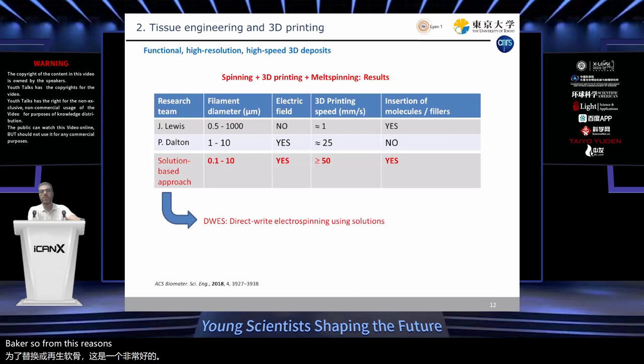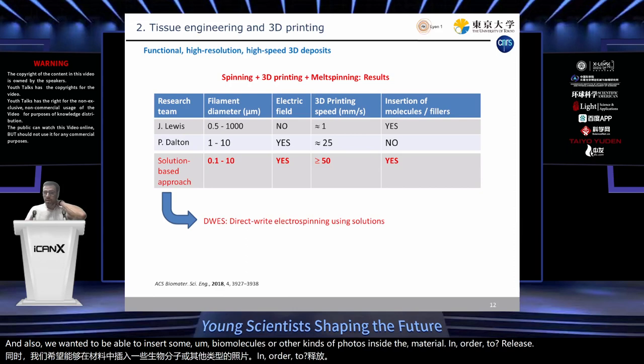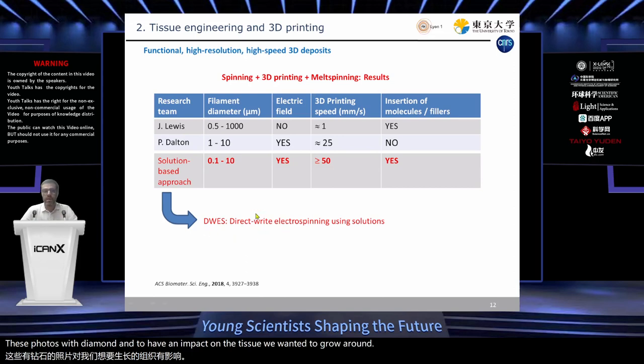So from these results, in our case, we were interested in keeping the very small size of the filaments, or the object we were printing. So filaments of about several tens to hundreds of nanometers to 10 micrometers, in order to stay in the range of the size of the cells and to be able to print quite rapidly the object. And also we wanted to be able to insert some biomolecules or other kinds of fillers inside the material in order to release these fillers with time and to have an impact on the tissue we wanted to grow around. So we decided to work on direct writing electrospinning using solutions.